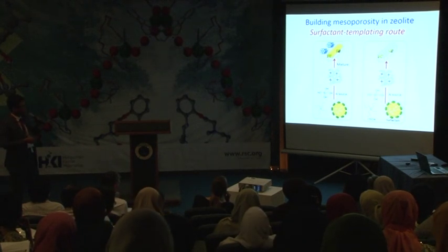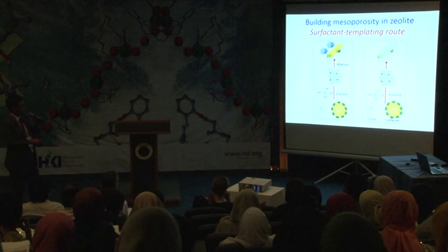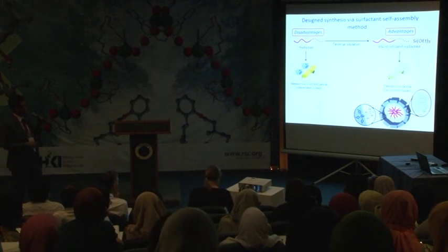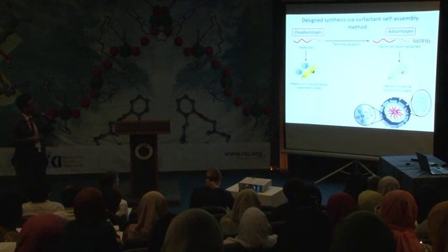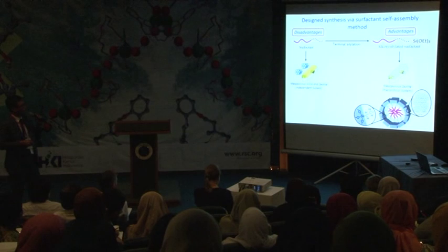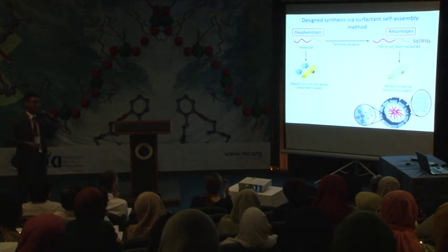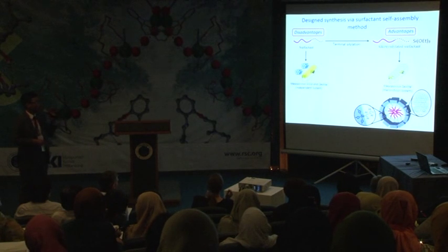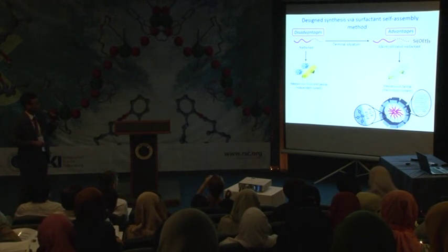So in order to direct into these directions, we are using such modified surfactants. This modified surfactant has an added alkoxysilyl group. It can hydrolyze into the silica network, which is then crystallized into zeolite.